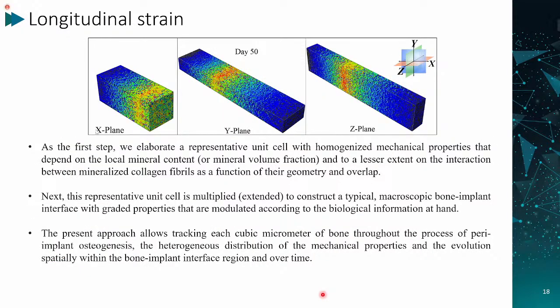So at the first step, we elaborate a representative unit cell with homogenized mechanical properties that depend on the local mineral content or mineral volume fraction, and to a lesser extent on the interactions between the mineralized collagen fibrils as a function of their geometry and overlap. Next, this representative unit cell is multiplied to construct a typical macroscopic bone implant interface with graded properties that are modulated according to the biological information at hand. So the present approach allows tracking each cubic micrometer of bone throughout the process of peri-implant osteogenesis, the heterogeneity distribution of the mechanical properties, and the evolution spatially within the bone implant interface region and over time.